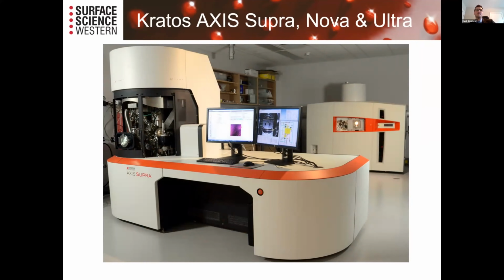It's got an aluminum K-alpha source, a silver source. You can heat the stage up to 800 degrees, cool it down to liquid nitrogen temperatures. You can fracture samples in situ in the vacuum. There's a glove box that hooks up to the front end of the instrument somewhere right about here that you can introduce air sensitive and water sensitive samples. It also has a gas cluster ion source, which allows you to do depth profiling through soft materials.